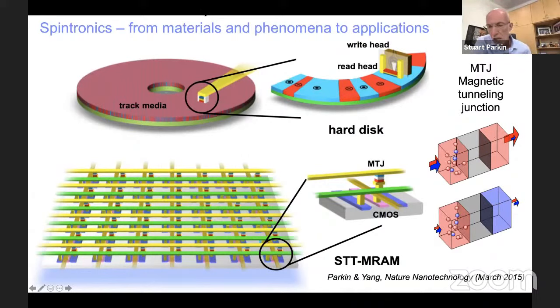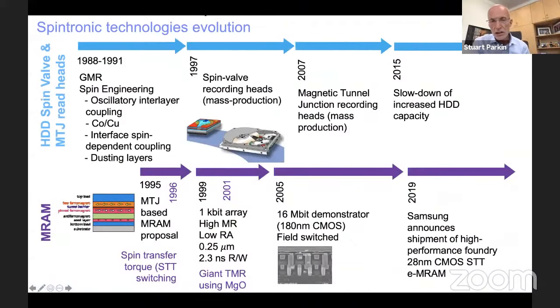This tunneling junction then has been used as a sensor for about the last 10 years. And in 1995, we and Jagadeesh Moodera proposed we could use the same tunneling junction as a memory element. The information is stored simply as the direction of the magnetization of one of the layers. And because of this very, very strong tunneling magnetoresistance, which means the resistance of such a device depends strongly on the relative orientation of the two magnetic electrodes, these pink and blue layers, we can easily detect the state by passing a tiny current. I want to just briefly discuss the evolution of these two spintronic technologies. I think it's very interesting.